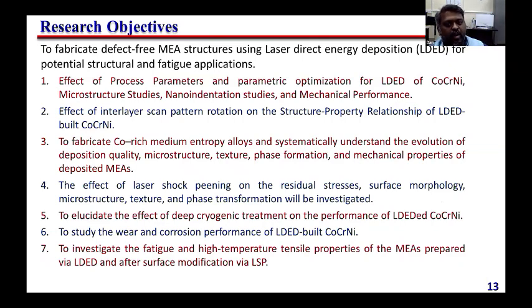And also we tried to change the composition. We have taken cobalt rich and cobalt lean in this particular three component alloy, and then tried to see what microstructure and structural property changes occur. Finally, we tried to see how laser shock peening, one of the surface modification techniques, affects the additive manufactured sample. Also we did some post processing by cryogenic or heat treatment. Our students are still working on wear and corrosion study. I will try to show you three or four objectives, what we did and what result outcomes we got. Then I will go ahead with some of the high entropy results.